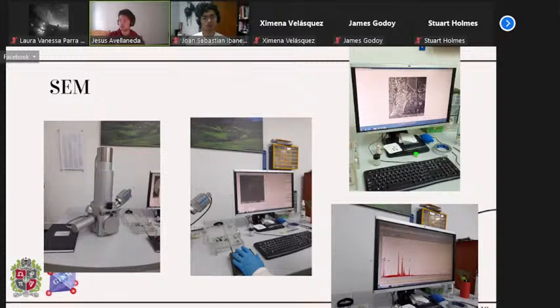But also to rule out some possible contamination, as you can see right here. EDS was performed, as I said, to see if there was some contamination to take into account, and in that case, to see which kind of contamination there was. Our biggest concern, although it was somewhat expected, was aluminum contamination, given that the crucible where all the sintering process was carried out was always the same and was made of alumina too, so it could interact with our sample between thermal processes and induce some kind of contamination. But in this case, we didn't have a contamination to take into account.